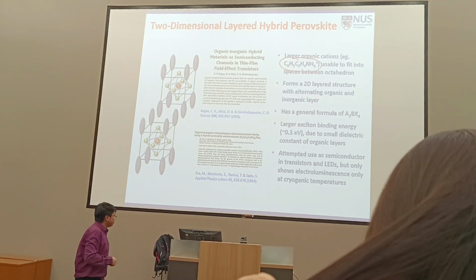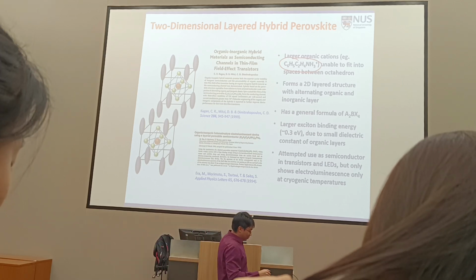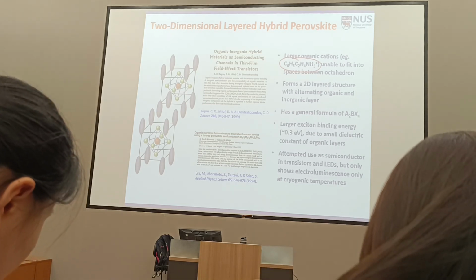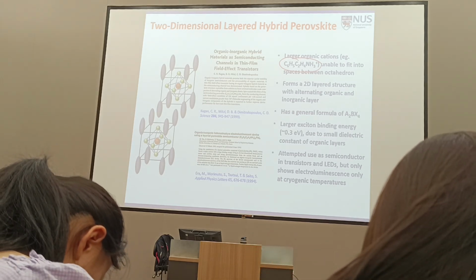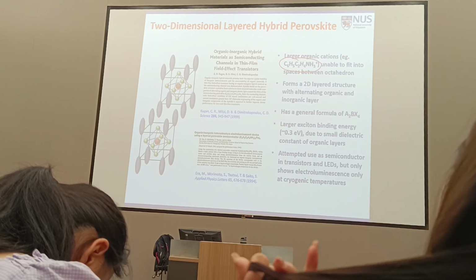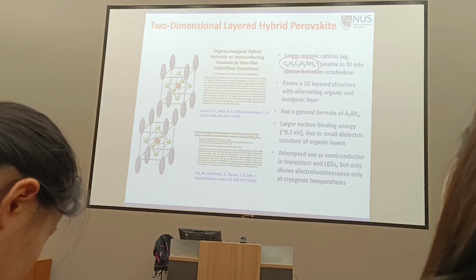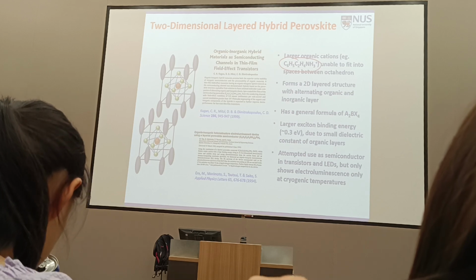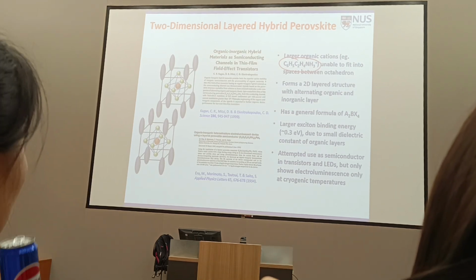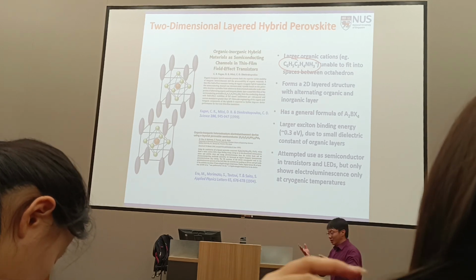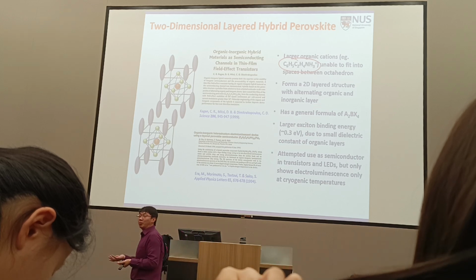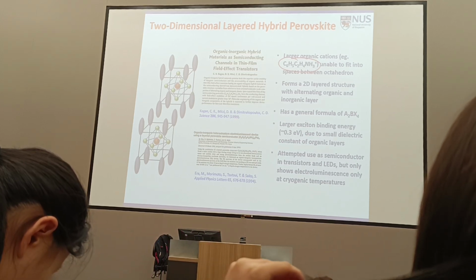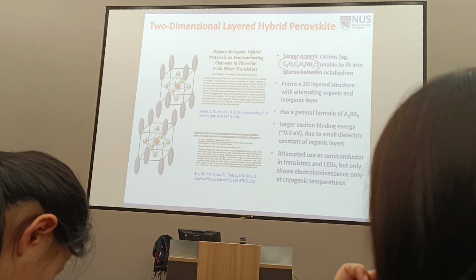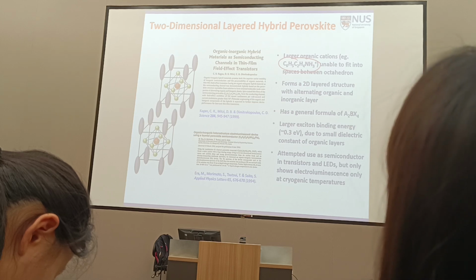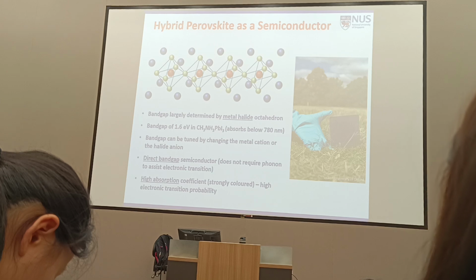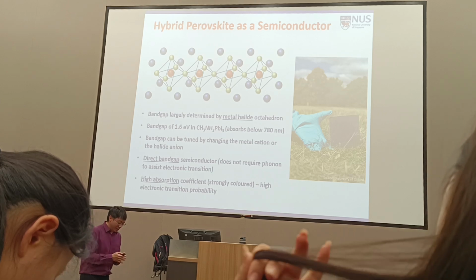What about LEDs? The first people to investigate this for LEDs only managed to get it to work at cryogenic temperature. That means they had to literally put the device in liquid nitrogen for it to light up. As you can imagine, it's a nice result, a nice demonstration that this can emit light, but not very useful. You need a super cold environment for these to light up efficiently. So what's the point? Again, there was a momentary excitement, and then after that, this wave died down, until recent years.